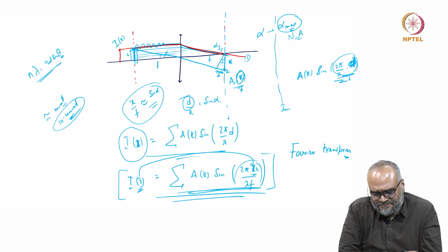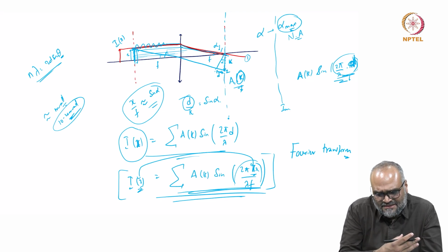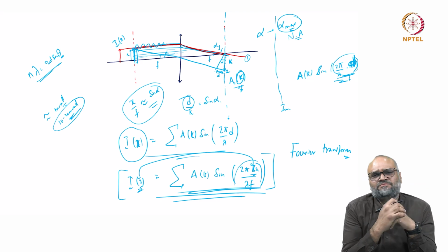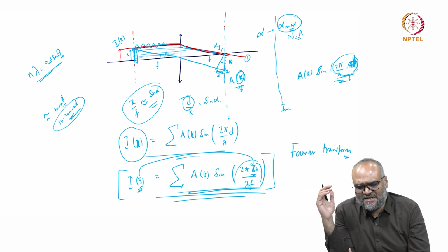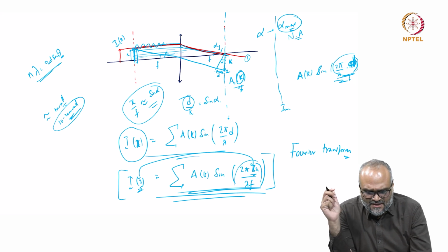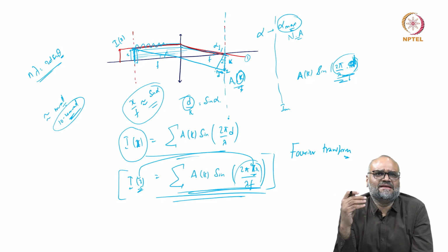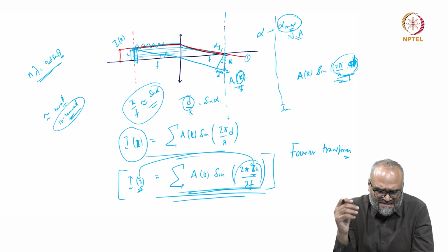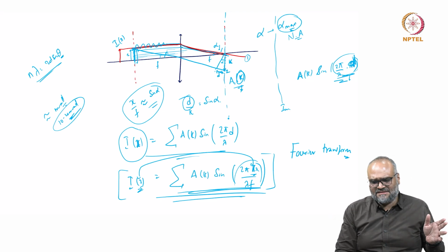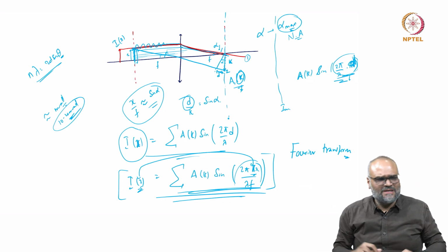So essentially, the information from a crystallographic sample I get from the real space can be related to what is called the reciprocal space at the back focal plane of an objective lens. And this is what happens within an electron microscope, and this is the function of a lens. So essentially, a lens transforms the information you get in a spatial domain to a frequency domain.